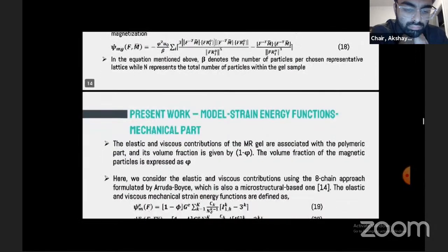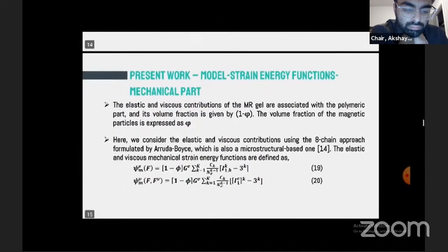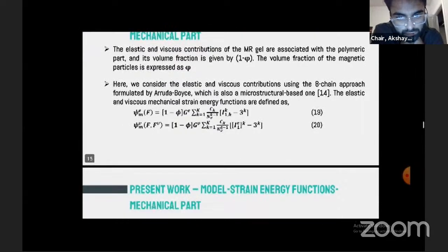Now, the magnetic part is done. We'll move on with the mechanical part. The elastic and viscous contribution of the MR gel is associated with the volume fraction. The volume fraction of the magnetic particles is considered to be phi, so the rest of the part contributes 1 minus phi. Using Arruda-Boyce's 8-chain approach, the elastic and viscous contributions, which are also microstructure based, the strain energy functions are defined as shown in equations 19 and 20.